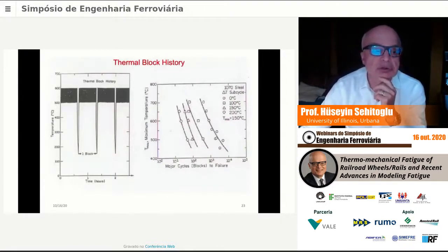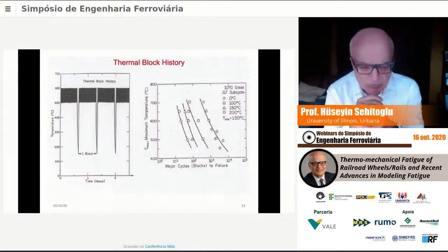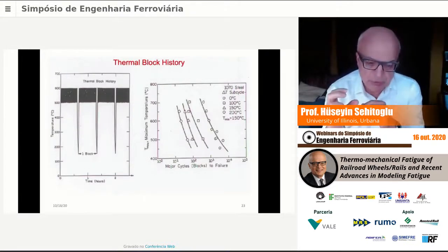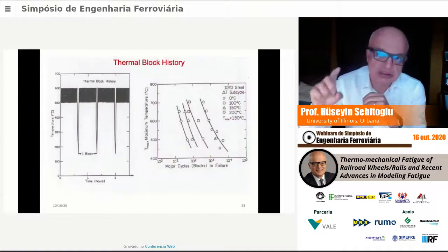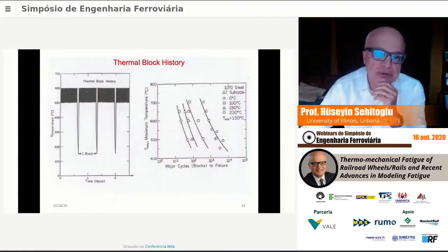If we look at temperature versus time, you could have a history like this, a thermal block history. In that case, as the wheel rotates, it sees the high temperature input from the brake, the brake is applied, and then it cools as it rotates. So history-wise, it goes through a cooling cycle. It's possible that there are lots of little heating and cooling cycles when you apply the brake. It's not just one major heating and a cooling cycle, but there are lots of little heating and quenching events in that area during the rotation of the wheel, because the rail cools that region as the wheel rotates.